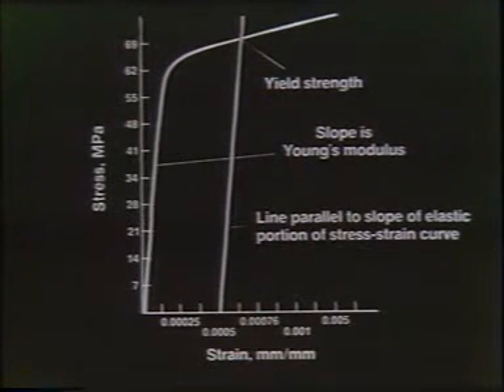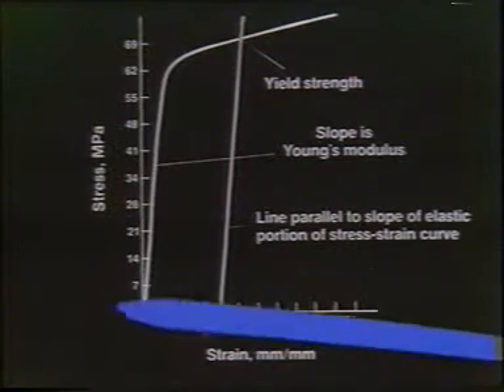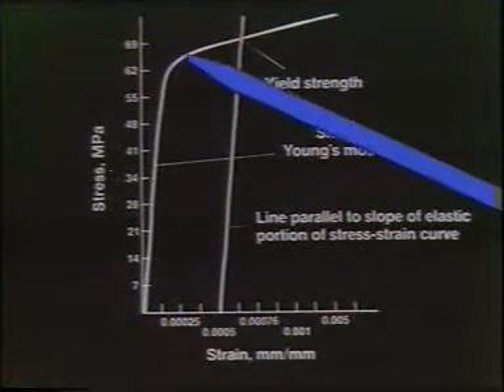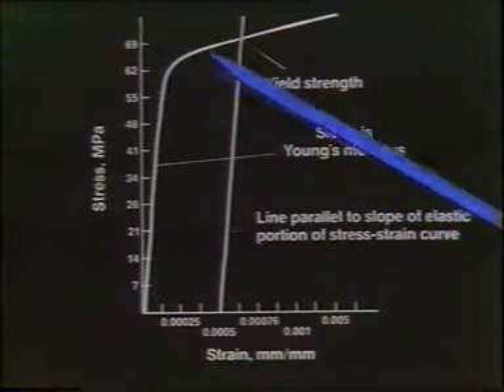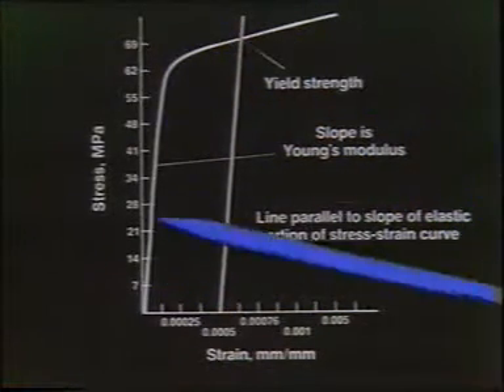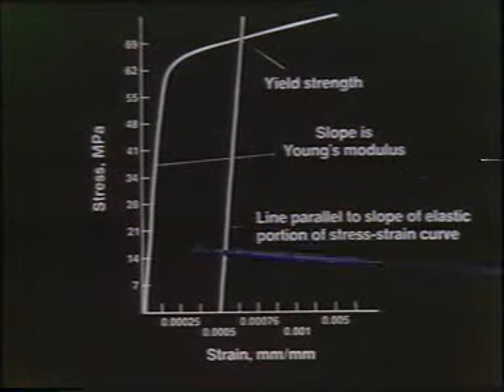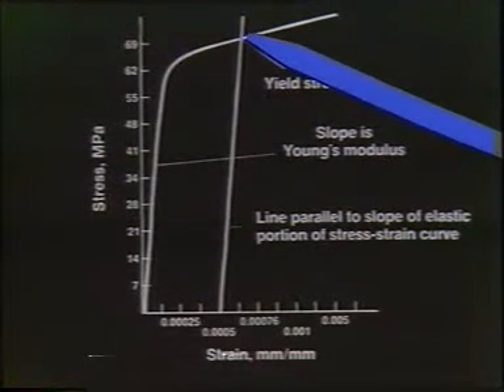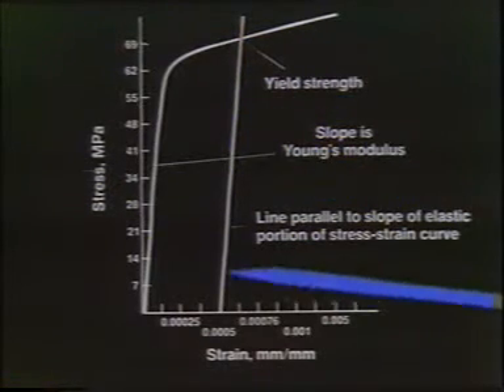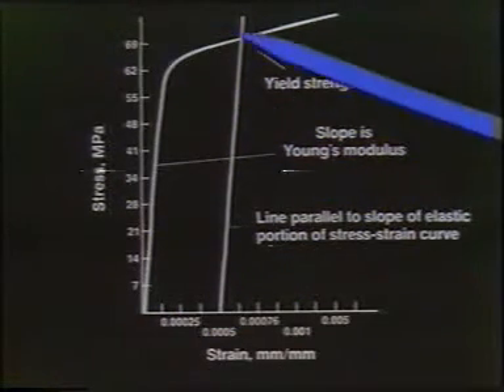If this were our stress strain curve, and we went up this curve elastically, the elastic limit may be somewhere in here, somewhere beyond this proportional limit. We don't know where it is, and it takes too much time for every material to load it up, unload it, load it up, unload it. And so what we do is, we know that when we get into the plastic region up here somewhere, if we unload the material, it will unload with a modulus that is exactly the same as the loading modulus. So the slope of this line is also Young's modulus.